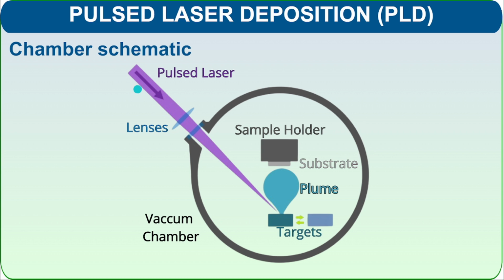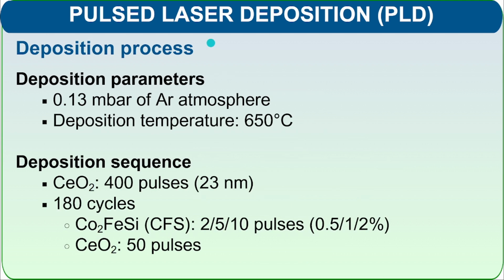Here we present a schematic of the chamber used for the PLD process. In this setup, a high-energy laser is directed onto the target material, generating a plasma plume. These plumes then travel towards the substrate. By alternating between two targets, we can have good control over the doping process. The depositions were carried out in a controlled argon atmosphere with our substrate at a temperature of 650 degrees Celsius.